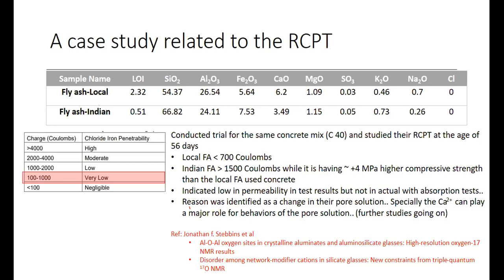So what we did was make the same kind of concrete with different fly ashes and test their coulomb values. The local fly ash delivered 700 coulombs, which is pretty good according to this categorization. The Indian fly ash delivered more than 1,500 coulombs, which is not good. But when we take the strength, the Indian fly ash delivered about 4 megapascal higher compressive strength compared to the local. I will come to that as well, and we'll discuss how the mechanism works.